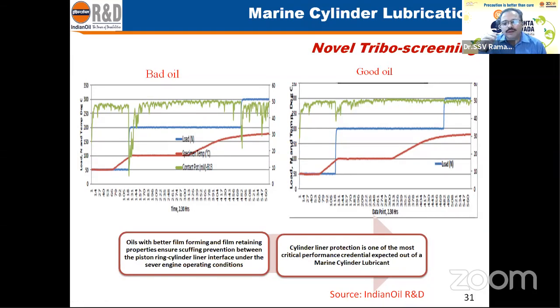The lubricant film between piston and cylinder liner, especially in huge marine two-stroke engines, cylinder liner wear is the key performance attribute expected out of a marine lubricant. And to optimize that, there is no other engine test, there is no other means. So we have devised this tribological screening, and see this: in a bad oil, you see these valleys in this graph, which clearly indicates that the film is forming between piston and liner, but it is getting broken. And such an uneven film will lead to catastrophic cylinder liner wear.